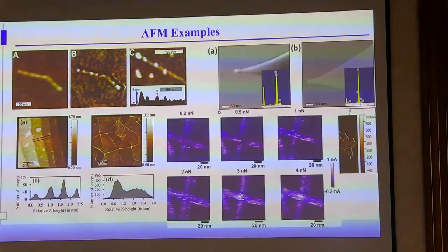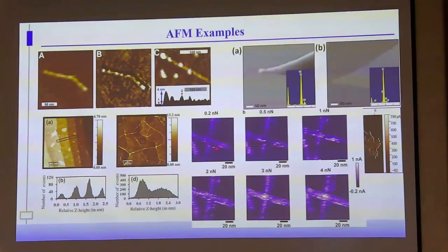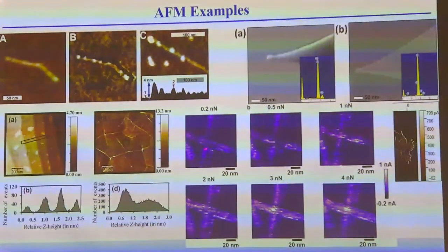Here we are studying the junction of carbon nanotubes, because carbon nanotubes have a very good interaction, but it's not necessarily that the junction is pretty strong electrically. So here you can see that in the first case it's not very conductive, but in this case it's very conductive.